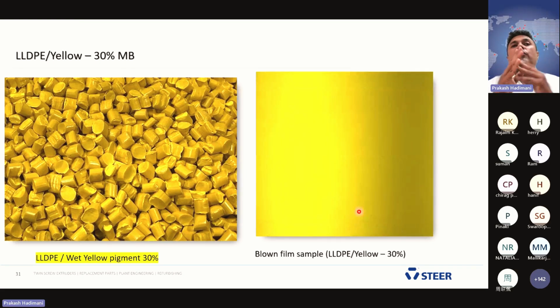In this case study, we have used two pigments. One is green 7, and also we have used yellow pigments. For yellow pigments, we have used 30% pigment and 70% water in the mixture. We also followed the same process: premixing polymer and wet pigment premix, fed into the twin screw extruder using a special feeding mechanism. Then we use dispersion and also dewatering of 70% of the water from the extruder. And we have taken the pellets.